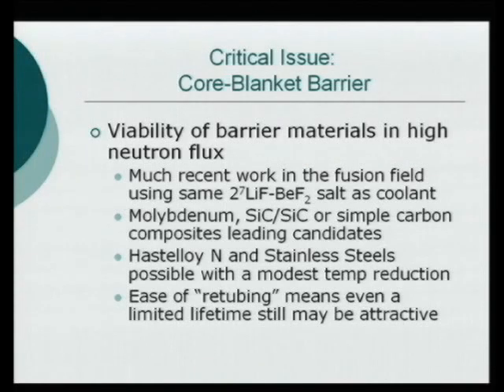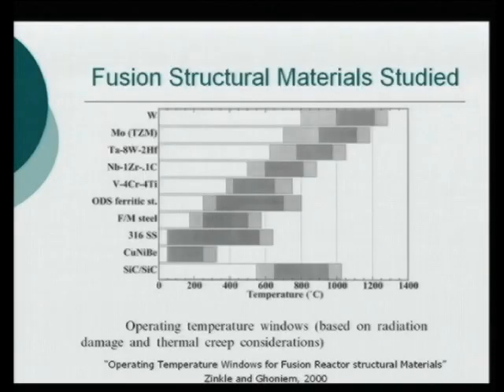And that's not really too big of an issue. It is a bit hard to make sure we have salts that have a low enough melting point. But if you lower the temperature a bit, we can really start to consider using stainless steels or the Hastelloy. And ease of retubing means, well, even if your barrier doesn't last forever, it's not going to be that expensive to fix.